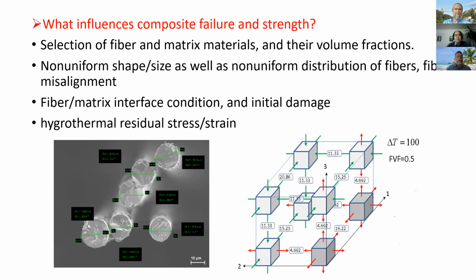For example, when you have the unidirectional composite without any physical constraint and then subject it to temperature change, then at the composite level, because there is no physical constraint, there is no thermal stress. They are free to expand or contract. But at the constituent material level, fiber and matrix, there are thermal residual stresses because of the mismatch of coefficient of thermal expansion.